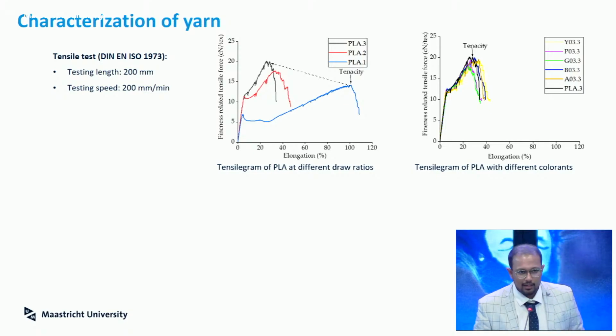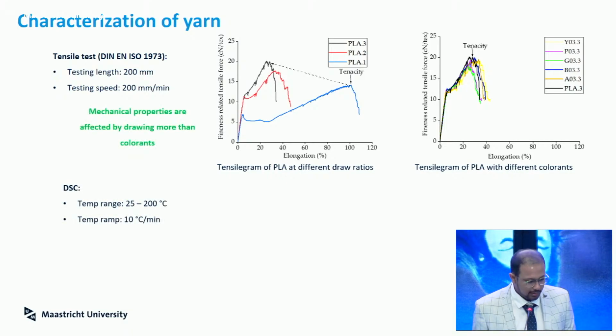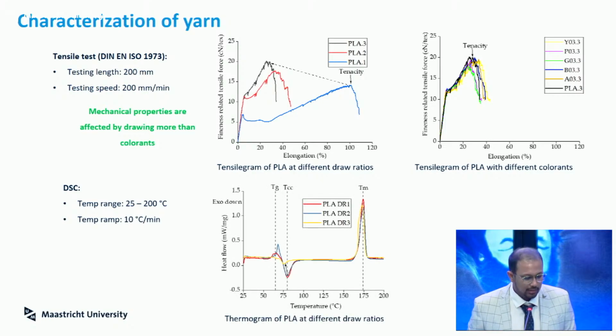On the right side, it shows a set of materials with 0.3% of colorants, under the same process as the pure PLA. And if you see there, upon addition of colorants, you don't see any big change in terms of strength or elongation, which is the outcome we also wanted. It means the mechanical properties were affected more by the processing that I did and less by the colorants I was using.